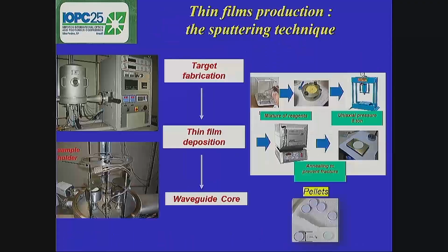And the thin films are produced by the sputtering technique. We use very simple equipment that operates in vacuum with argon gas, sometimes with a small concentration of oxygen, depending on the composition. We have 2 electrodes, so it's possible to perform co-sputtering of the materials. And at the top, the sample holders rotate during the process, and this improves the uniformity and the quality of the thin films.